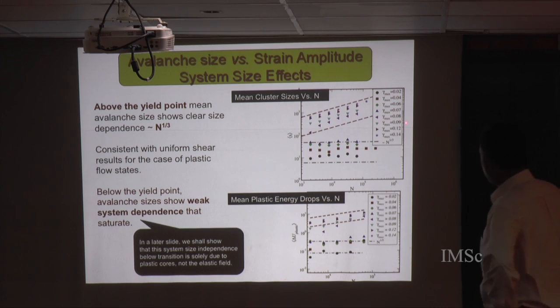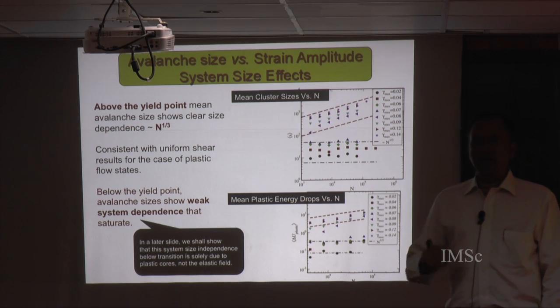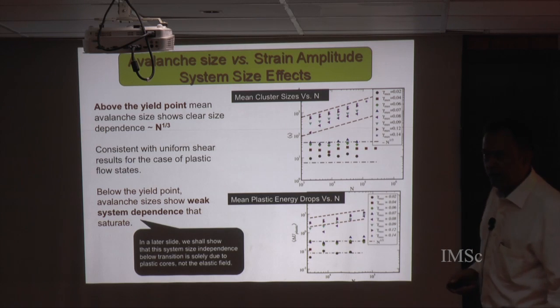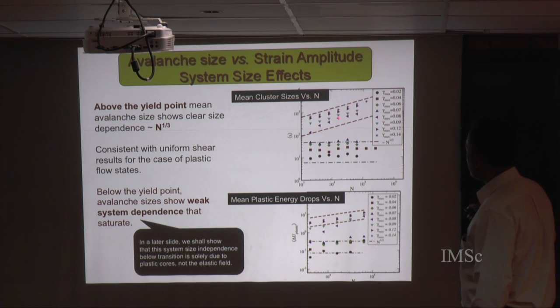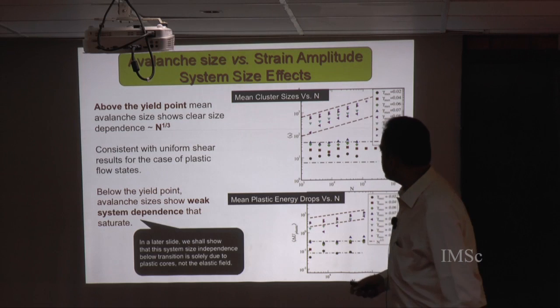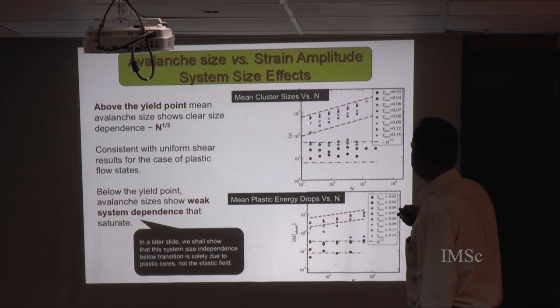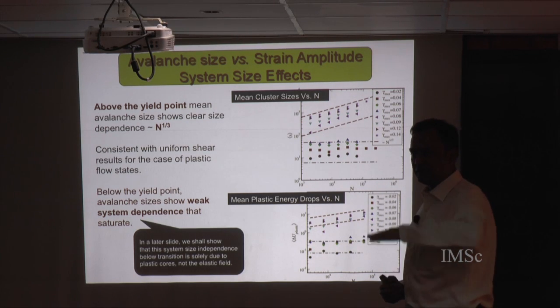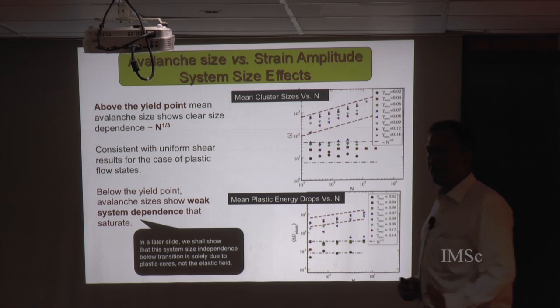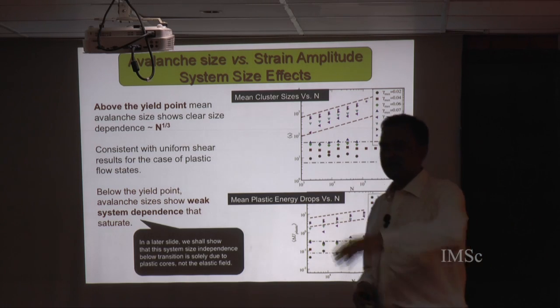But when you go beyond 0.07 onto 0.08, you begin to see that the mean cluster size has a very clear system size effect. Okay, and so the 0.08 case is where there's a bit of a crossover. So Ranjani, this is what I meant. So if in all the other cases it's one type of behavior or the other, but for 0.08 there is sort of a crossover behavior.